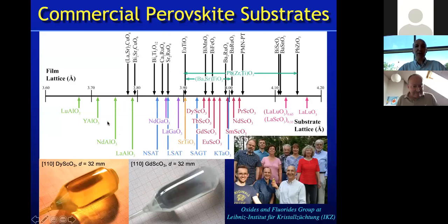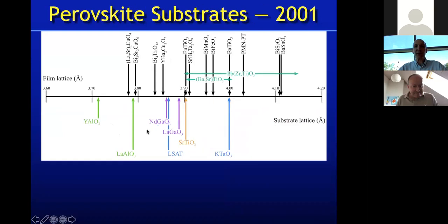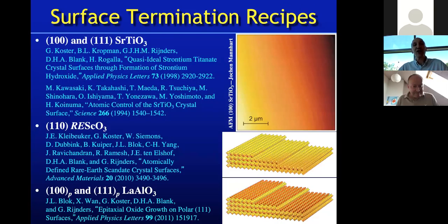I also should point out how fortunate we are today, where we have some 20 different perovskite substrates compared to just 2 decades ago. Two decades ago, and Jean-Marc will recognize how bleak things were back in the high-Tc cuprate days in terms of substrates, the number of choices was far lower, and having these really helps with epitaxial stabilization in the perovskite space. Now, maybe you're interested in other materials like rutiles and pyrochlores and spinels, where again there's a lack of substrates. There is one oxide rutile, there is one oxide spinel, commercially available large substrate. But that's a huge opportunity.